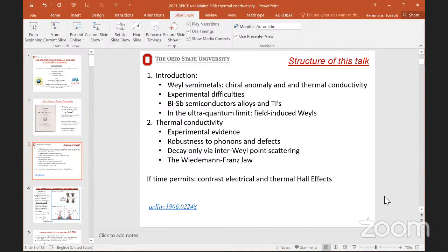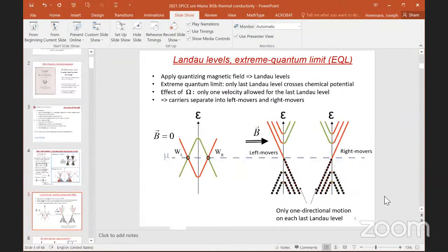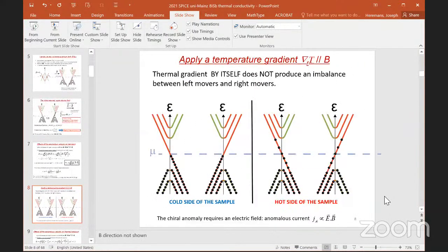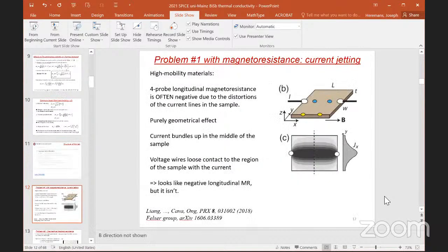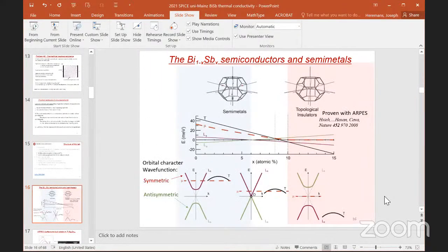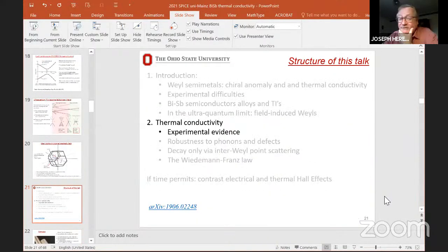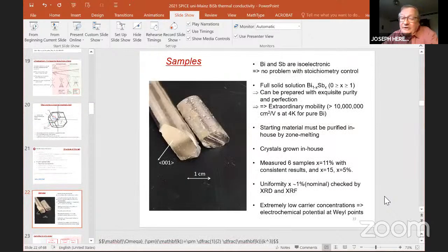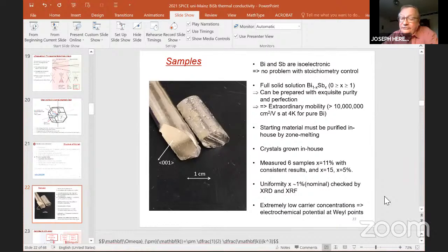So I have a question concerning the crystal quality. Do you have an idea or have you measured how the defect density in your perfect crystals varies from sample to sample? Yes. Well, our main measurement here is a mobility measurement at low field. And the mobility in our best sample was 2 million, and in our worst samples, which are Czochralski grown, is 20,000. I think that gives you right away an idea of the scale by which we can affect the defects.